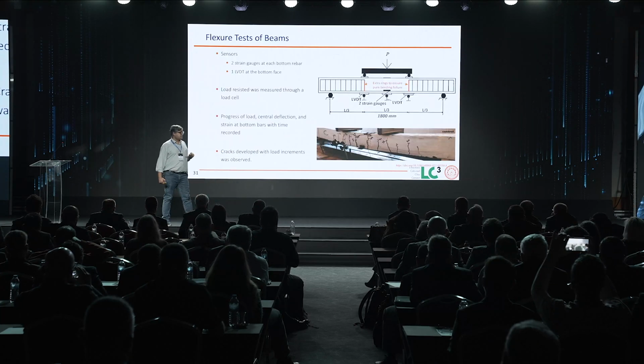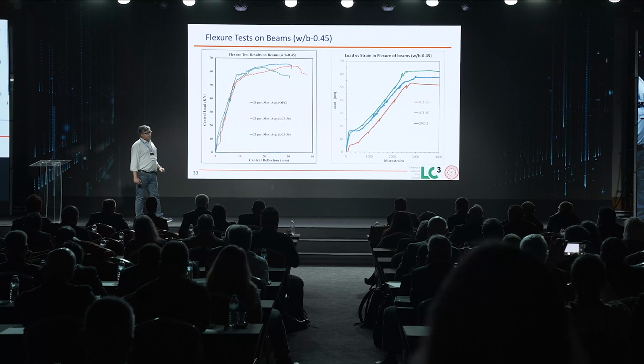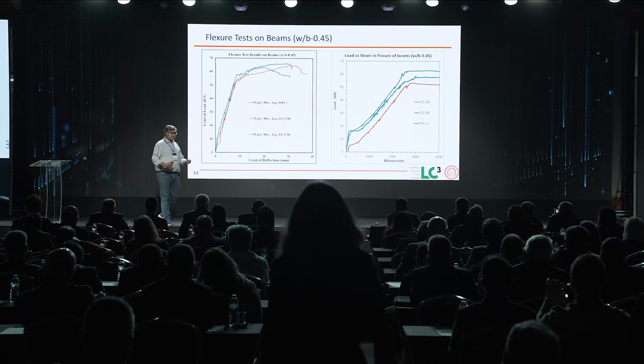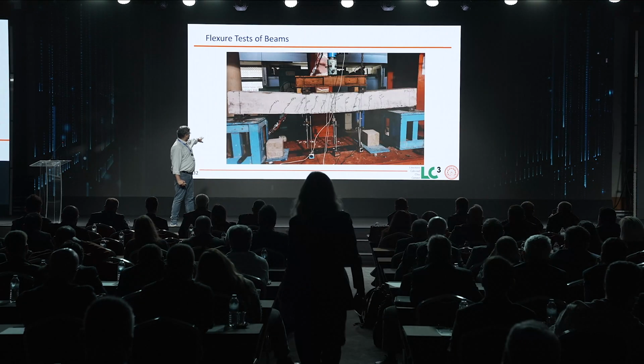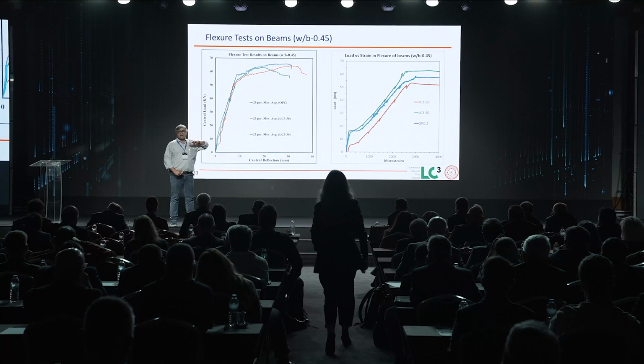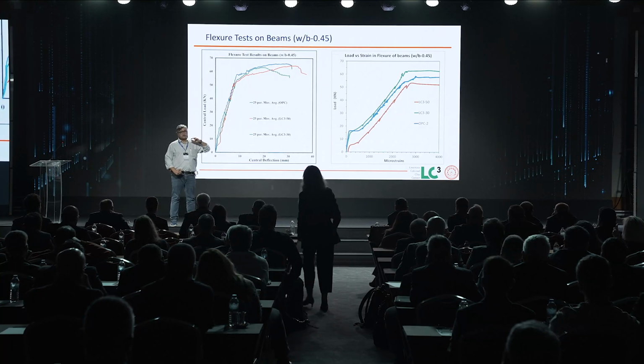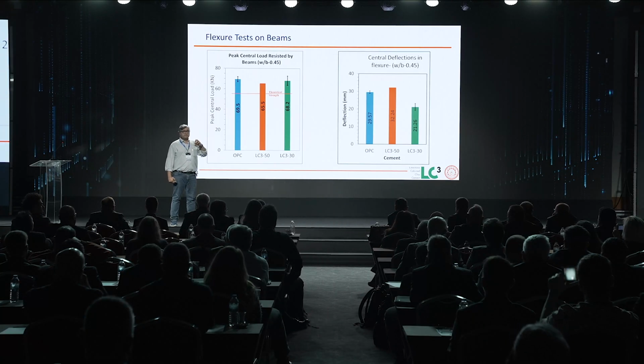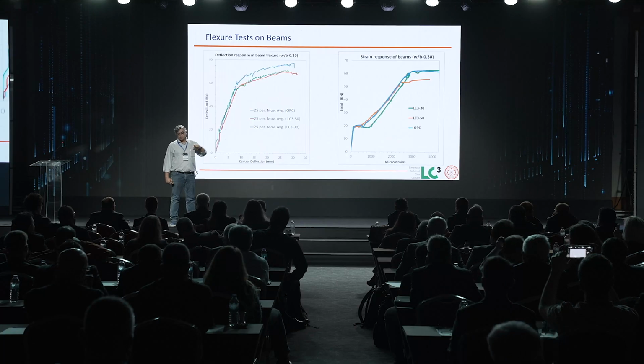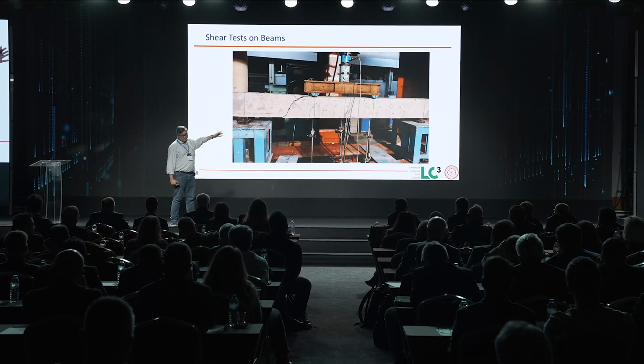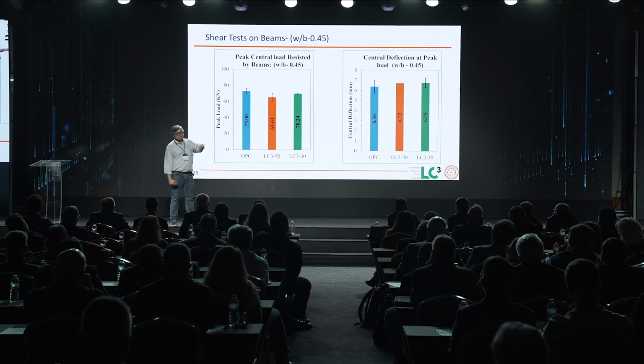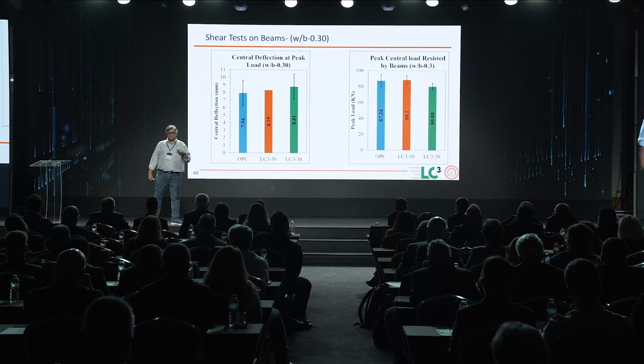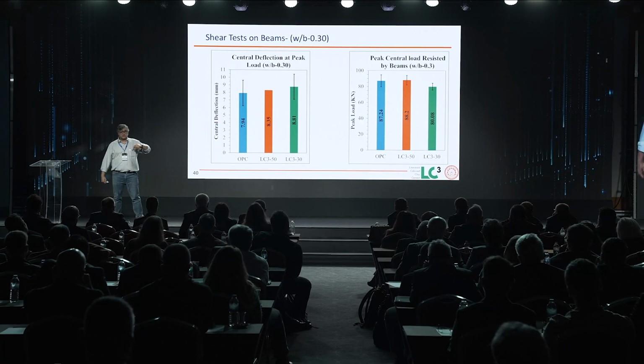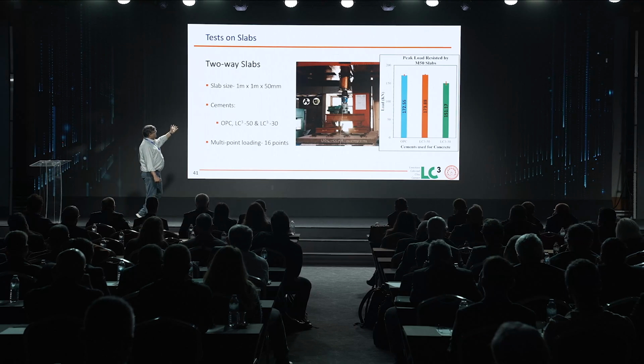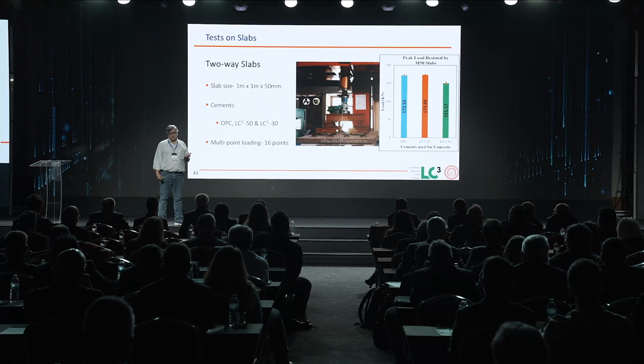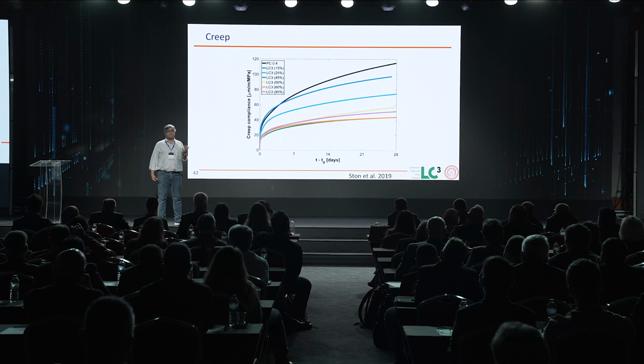A lot of structural tests in the lab, beams broken. I'm a civil engineer, like I said, I like to break things all the time. And we broke all those things, we did some measurements. LC3 30, LC3 50 performs very similar to OPC. Be it the flexural load that is being measured, be it the shear capacity that you're measuring in LC3 30, LC3 50, OPC, be it the deflection that you're measuring, be whether you measure it in the case of slabs, in the case of beams, you essentially get results which are very similar.